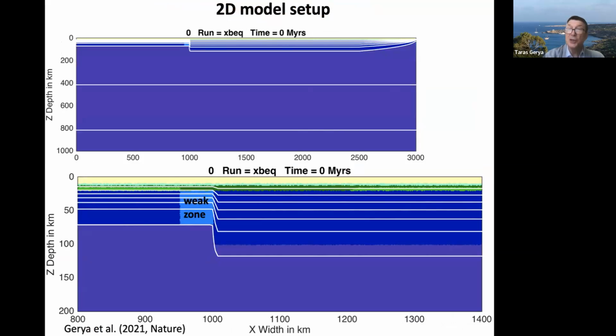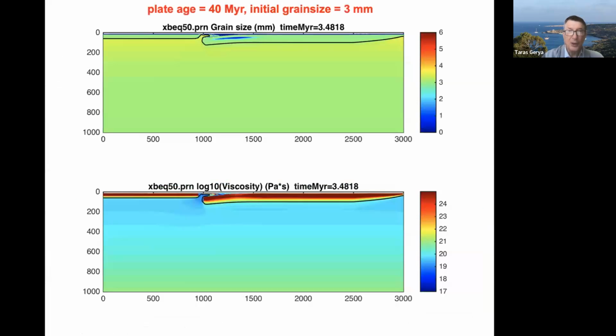So we have taken one of our standard subduction models. We were using the so-called spontaneous subduction initiation, which is, of course, by itself a debatable mechanism. But what we wanted was to avoid any uncontrolled forcing from ridge push or plate motion prescribed in the model. We just wanted subduction to start naturally and then see how the character of subduction will be affected by coupling of the brittle deformation on the top of the slab with normal faulting, and ductile deformation with grain size reduction and Zener pinning in the middle and lower plane of the slab. So, all the physics which we consider relevant for the slab deformation processes in the outer rise was placed into the model. And the result was quite surprising.